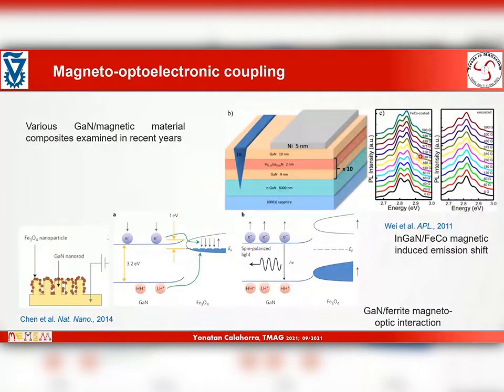So we can look at this case of a magnetic layer covering an InGaN emission stack. The magnetization of the layer can control the emission wavelengths. For example, as we see here, it doesn't happen in the uncoated control sample. There's also a spin optics example made using gallium nitride nanorods covered by ferrite nanoparticles. And the composite approach, even in gallium nitride, is working.